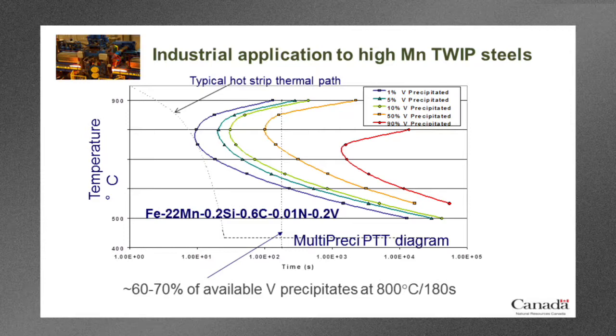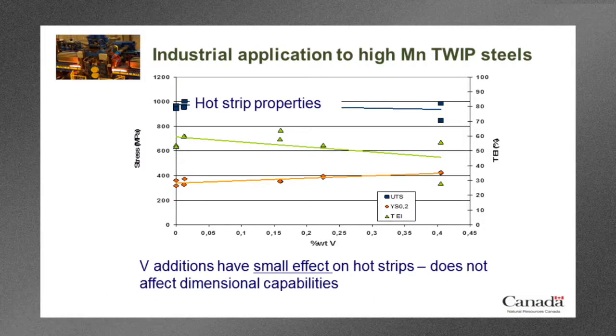And then after cold rolling, when we do this recrystallization annealing, you can see that we would be intercepting this orange curve, and that would be about 50% of the precipitated vanadium, which is very interesting. So it means that we can not change the strength of the material right up to the end of cold rolling, and then we will strengthen it during recrystallization annealing, which is exactly what we want to do. This is the hot strip.